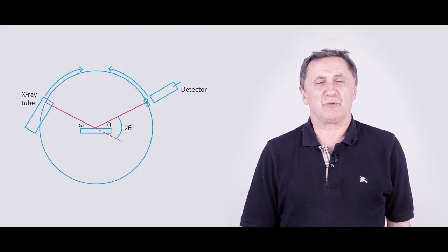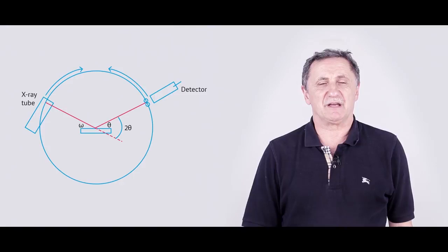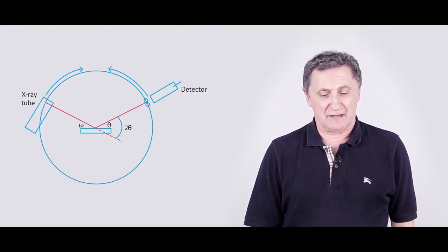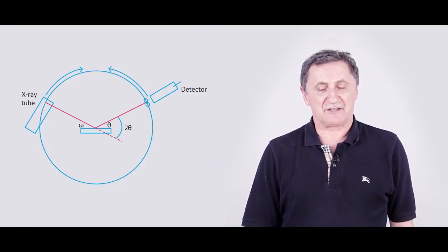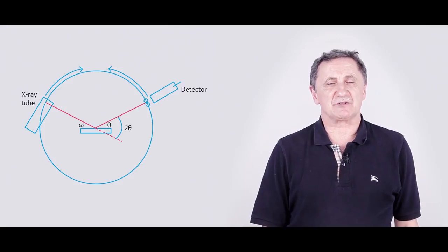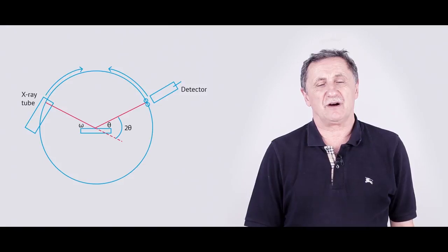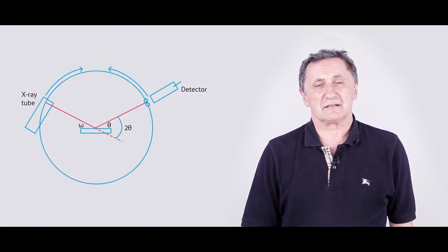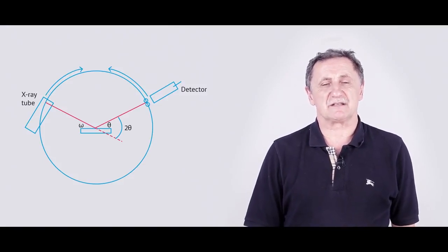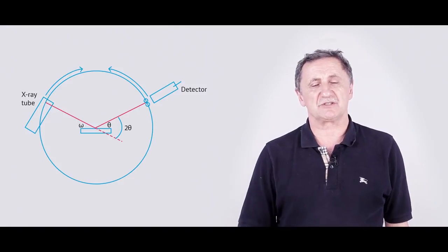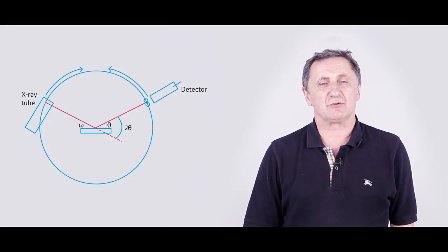So again, before we go, let's also talk a little bit about the space resolution. Typically the size of the sample should be on the order of several millimeters square, and the thickness of the sample should exceed about 100 microns.